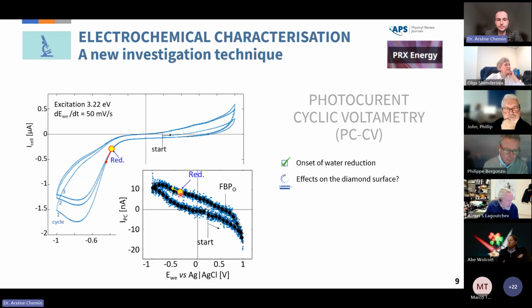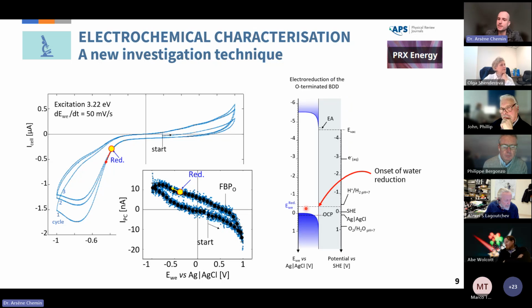And then if we continue cycling, we can actually observe here on the CV some reaction happening. This is the electrochemical reduction of the diamond surface. This happens because at some point, the potential of the electrode is above the reduction potential of the hydrogen. So we start reducing water, forming hydrogen ions and radicals that will reduce the surface of the diamond. And if we keep going, we will at some point measure a novel flat band potential, which is much reduced compared to the previous one. So you have this beautiful hysteresis inside the photocurrent. And this flat band potential corresponds to the hydrogen-terminated diamond. So it's another proof that we really managed to change the surface state operando, I would say, through the electrocatalysis of the surface.